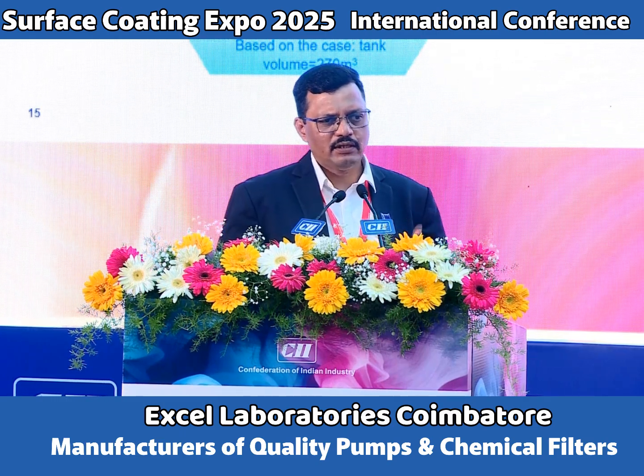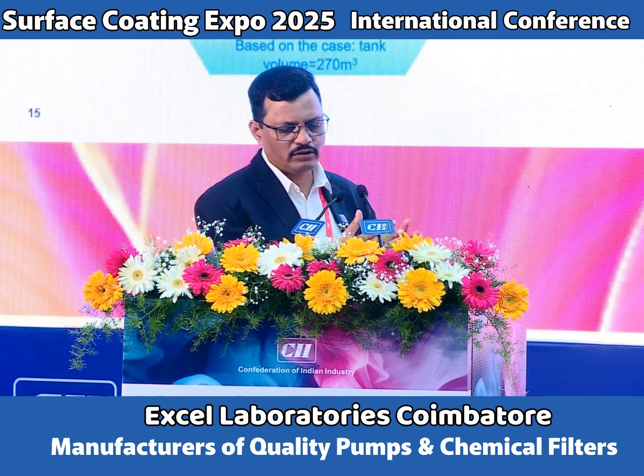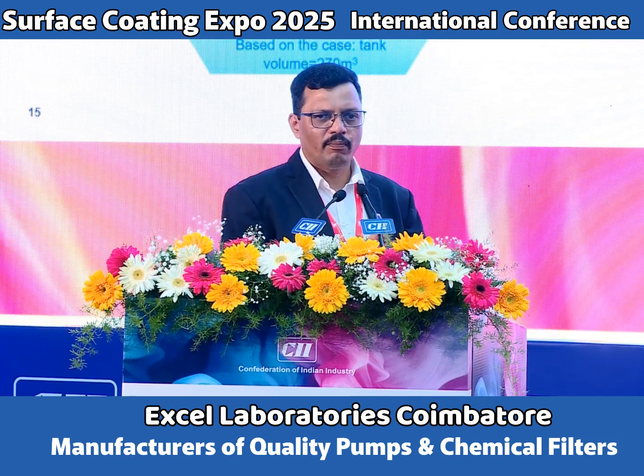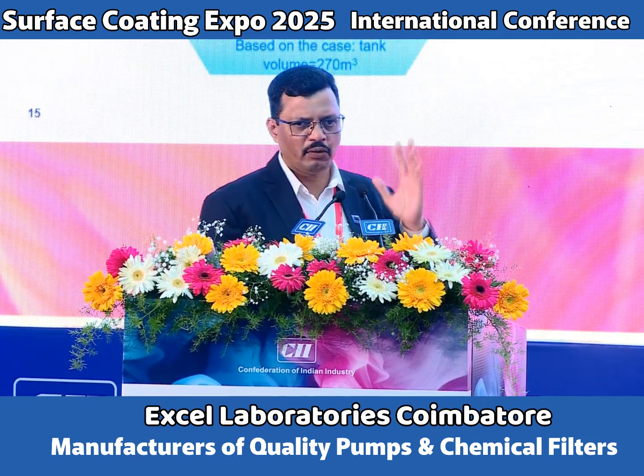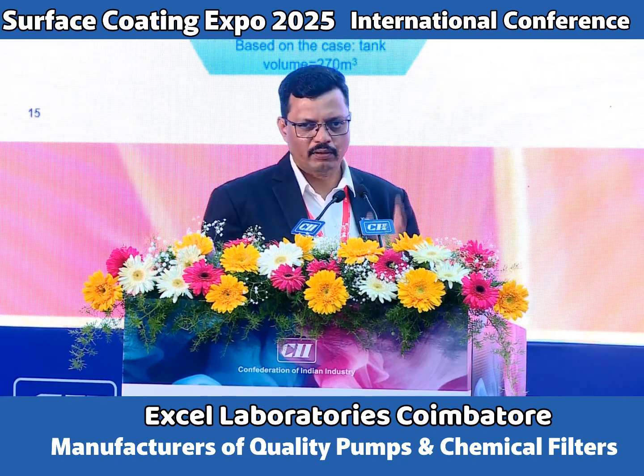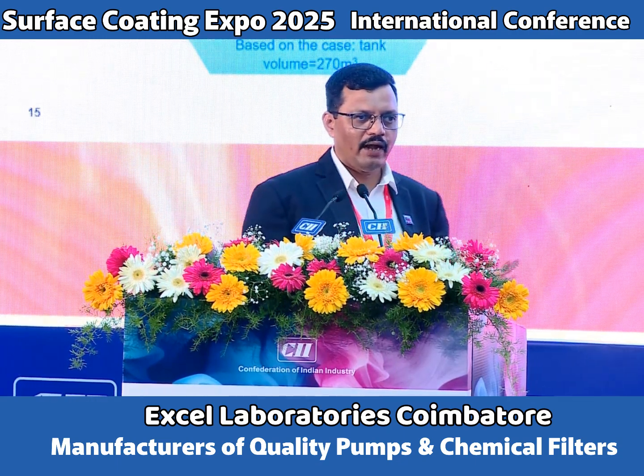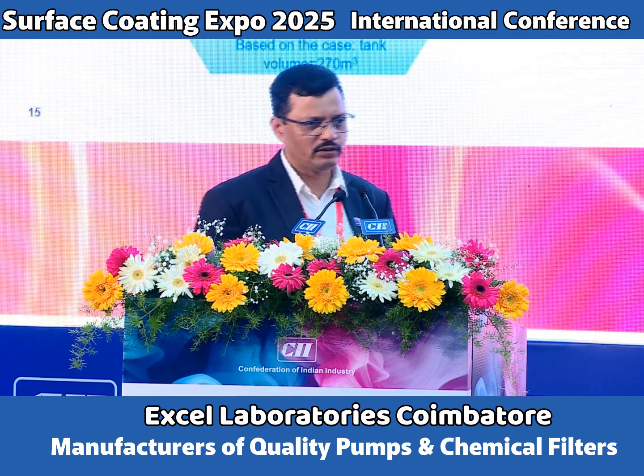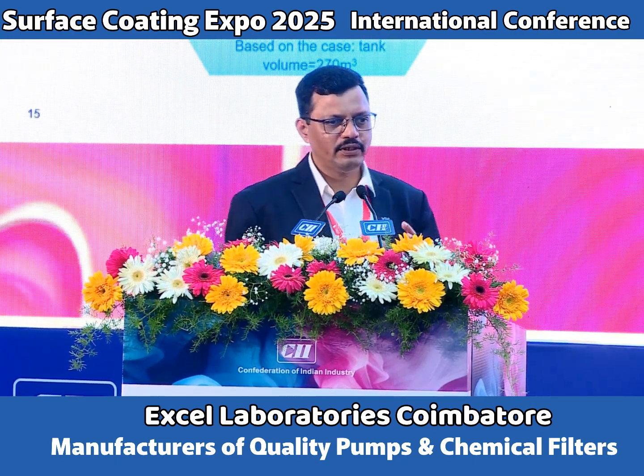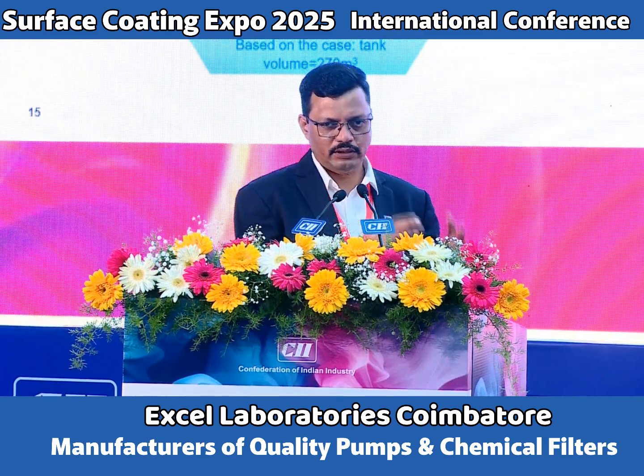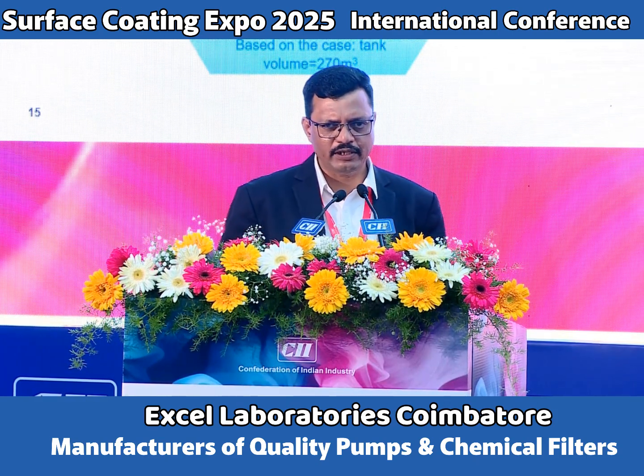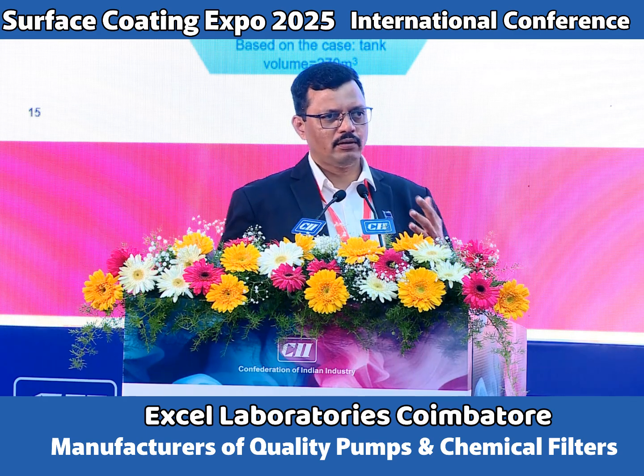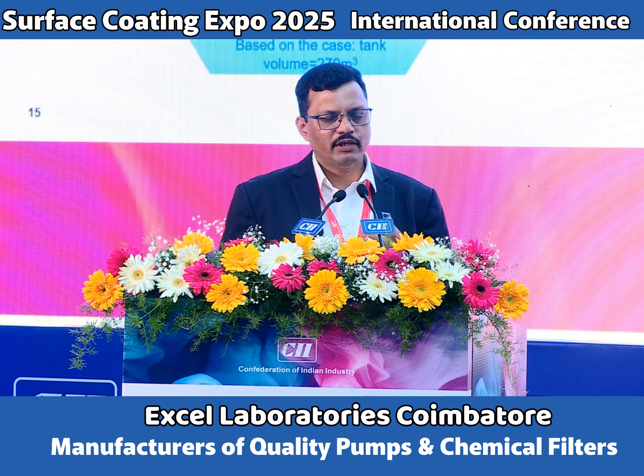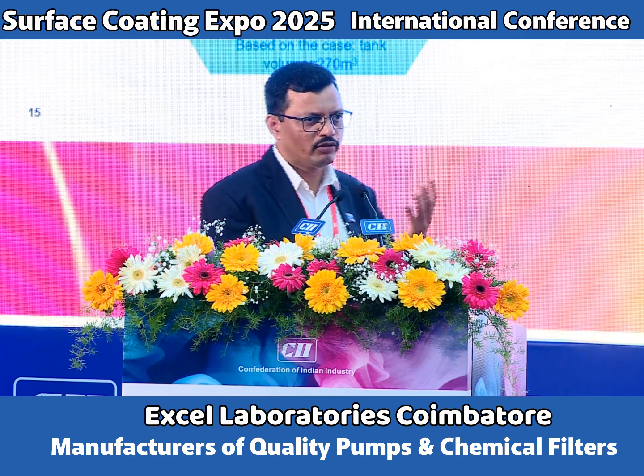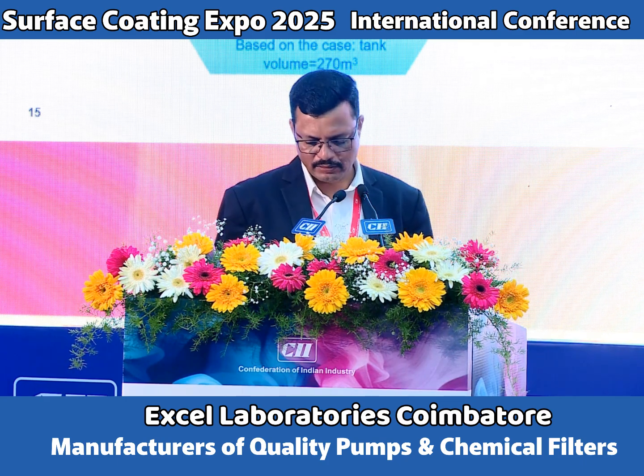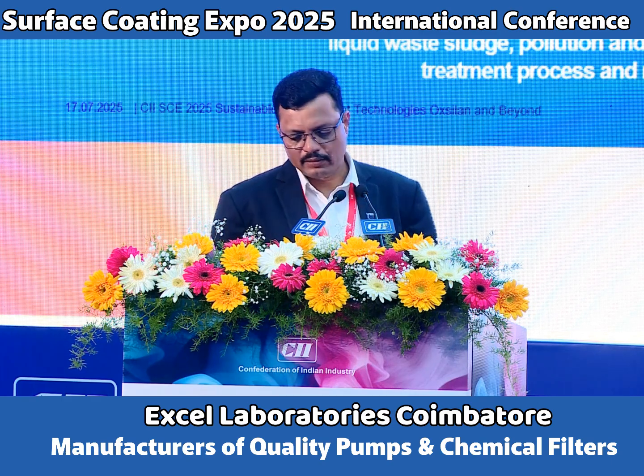So in conventional thin film processes, we used to have almost 3 or 4 products for makeup, and the concentration used to be somewhere around 30 or 40 grams per liter. Whereas in the advanced thin film processes like Gardobond X 4689 and 4688, we used to have very low concentrations of the initial makeup. Okay, similar case for the replenishment. We only need to have 2 products. Instead of that, in the conventional process, people used to add almost 3 products like neutralizer and the acidifier. So here we save, right?